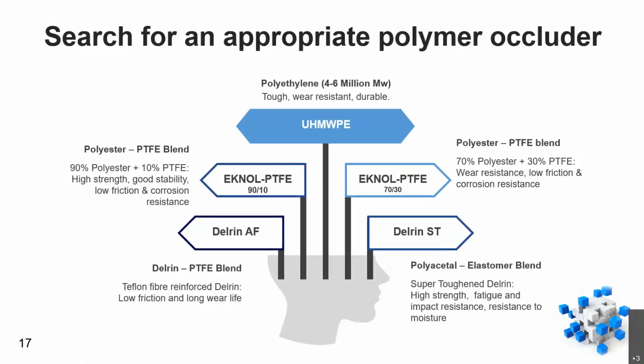Now let us get into some of the technical aspects of this particular development. When the sapphire disc failed in the titanium nitride sapphire combination, we had to look for a material which is soft, which has good toughness, and will last for 50 or 60 years without any corrosion, degradation, etc. So we chose many materials like Delrin ST, EKNOL-PTFE, then Delrin AF, and ultra-high molecular weight polyethylene, and did a series of studies to find out the durability of these materials. Finally, this ultra-high molecular weight polyethylene came out as the best candidate.